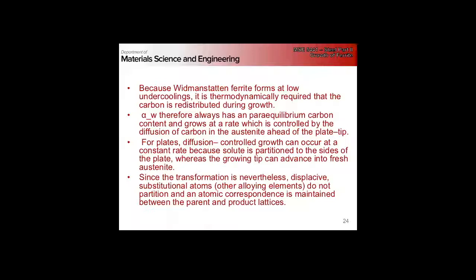So carbon does partition - again, we're always at para-equilibrium, and we're going to grow at a rate controlled by the diffusion of carbon ahead of the plate tip. Okay, so unlike idiomorphs, which are growing out in all directions, here we're growing along a plate.